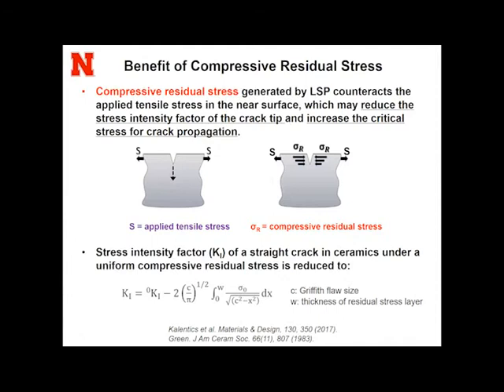The basic explanation for those mechanical property improvements, I would like to use the example by Kalentics in his paper. So if you consider the case without any compressive residual stress under the tensile load, the straight crack will propagate quickly in ceramic because ceramics are very brittle. But if we have built-in compressive residual stress, those can reduce the stress intensity factor at the crack tip. And also, because of compressive residual stress, it will increase the threshold for the critical stress for crack propagation.